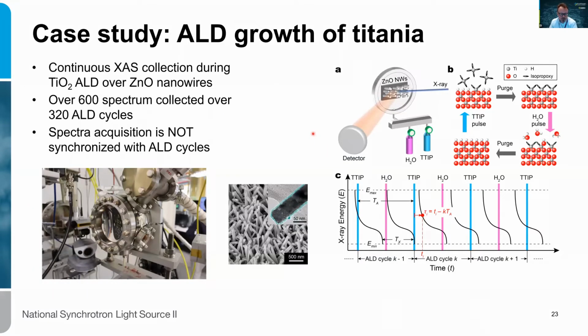All right. Let me talk about the next example that describes a rather unusual experiment in terms of how we conduct it, which is the investigation of the growth by ALD of titanium oxide on zinc oxide nanowires. This is the SEM image of these nanowires, and the titanium oxide here is covering the zinc oxide. So if you know how ALD works, you add the precursor, the organometallic vapor, to your substrate that adsorbs, and then you add the pulse of water or oxygen to remove the ligand, and this is how you grow the material layer by layer, hence the atomic layer deposition.